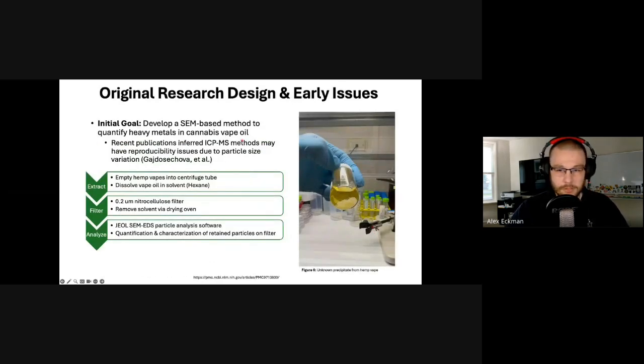So getting into our original research design, this was off of the back of some published research that showed that the current means of heavy metal methods may have reproducibility issues based on the particle size. And I'm going to butcher his name if I pronounce it here. So there is a link to the original study there. But what we thought we could do is simply dissolve the contents of a vape in some hexane. We would then pass that through a nitrocellulose filter, which would catch any of the particles that would potentially have leached out into the distillate or vape oil. We would simply remove the solvent and then place our filter under our newly acquired scanning electron microscope and utilize the EDS particle analysis software to count and characterize any of the retained particles.